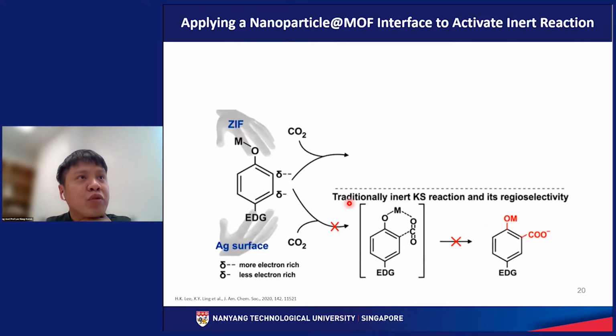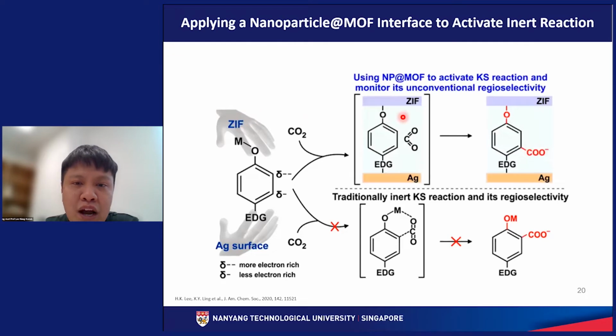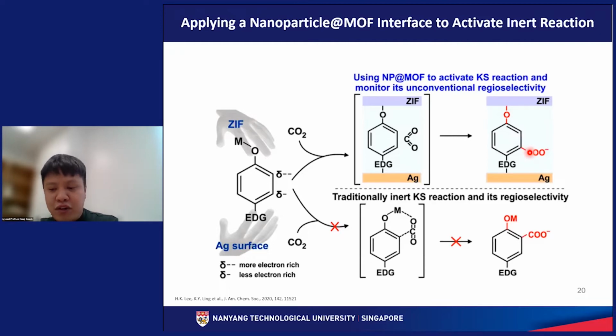But in our design, we try to use silver surface as well as the MOF layer to control the selectivity of our reaction. So in the meantime, we also want to apply our pseudo high pressure microenvironment inside the interfacial cavity to activate and drive the carboxylation reaction between our substrate with carbon dioxide to form carboxylate. So another point to note is that instead of having the ortho product, right now we are able to form the meta product. So this will be discussed more in depth subsequently in our slides.